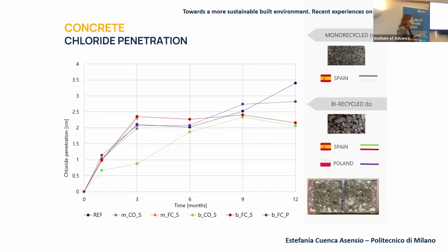Also, we analyzed a lot of properties. For example, just to show some of them, we tested these concretes against chloride penetration. We prepared cylinders and waterproofed all the surface. Only from one side did the water with chlorides flow, to simulate our marine environment. That's why it's easy to understand that it is a unidirectional flow of the water, and then with a cross section of the cylinder we can observe the progression of the penetration of chlorides inside the specimen. As you can see, in chloride penetration the better behavior in our case was the double recycled with coarse only from Subterra.